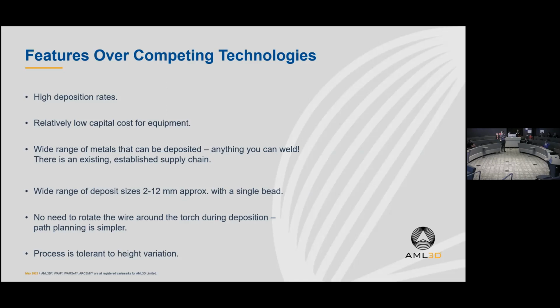In terms of the bead size of the deposit, we have got down to about 2 millimeters thick, but that really is a very narrow end. Normally, we're around 10 millimeters wide. The second to last point there is an interesting one. With TIG or plasma welding, you have an external wire. So with the MIG process, which is the one that we use, the wire is coaxial to the torch, and when it comes to making a part, that makes it a lot easier because you don't have to worry about rotating this external wire feed around the torch.